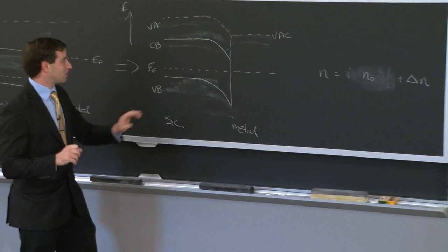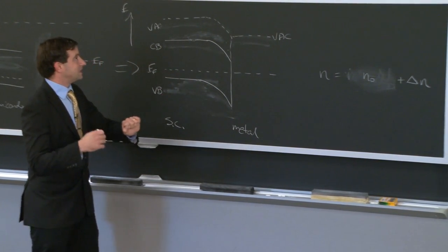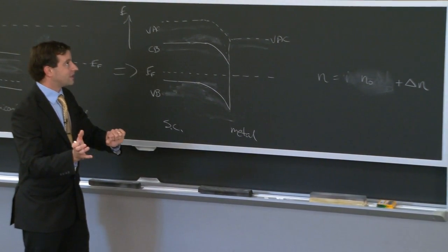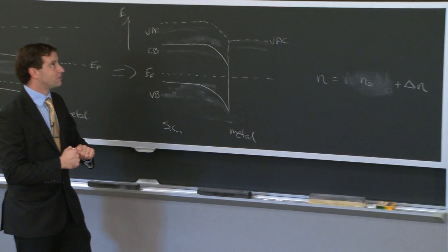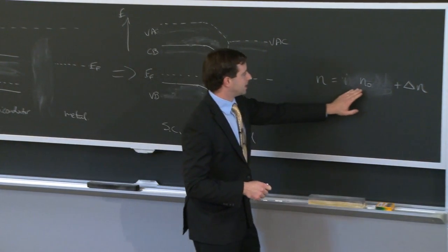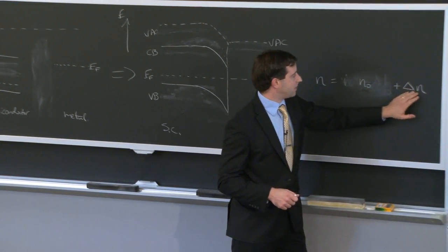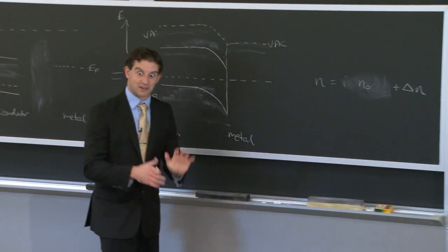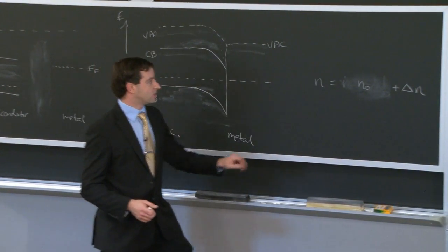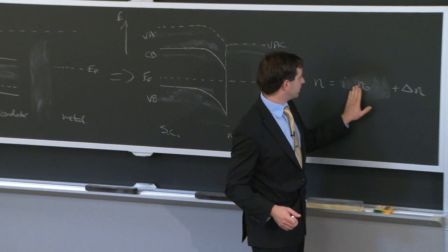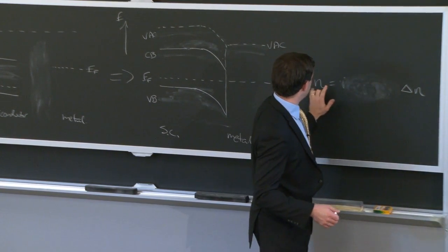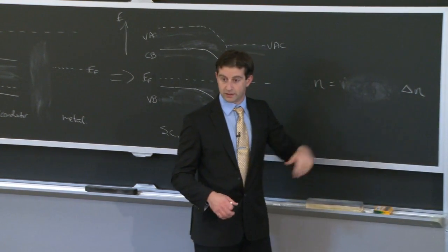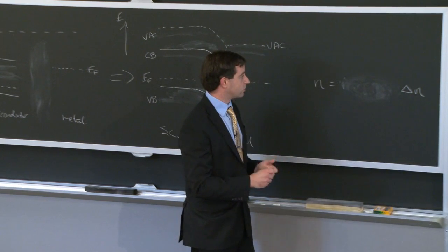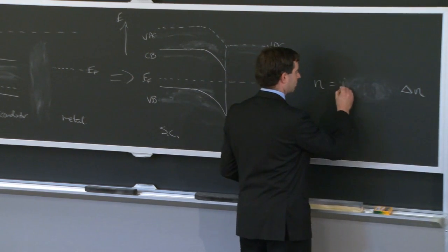And if P naught is on the order of, say, 10 to the 16, Ni would be on the order of 10 to the 10. We'd have something on the order of 10 to the 4 for our N naught. That would be a rather small number. Now if I inject light on it, I could have, say, 10 to the 14 electrons being created. So this drowns out everything else. So now my electron concentration is going to be driven by the photoexcited carrier concentration.